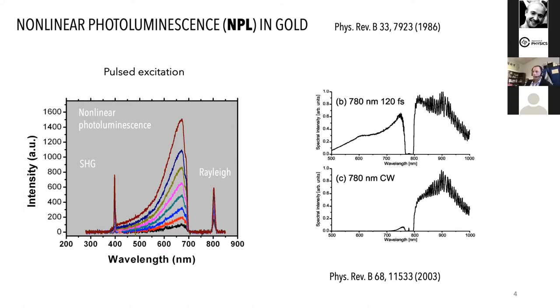Of course, you will also find another nonlinear effect in gold, which is second harmonic generation. You can see it on that very peak here, which is at double the frequency of the laser. I'm not going to be talking about that peak today. This would be a matter for another talk, okay? We're going to be focusing essentially on this up-converted nonlinear photoluminescence. On the right-hand side here, you see very similar spectra taken also from a gold nanostructure back in 2003. These are spectra that we took with Mike and Lucas.